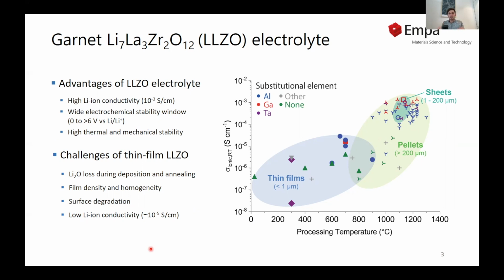On the lab bench, they are typically processed in the form of millimeter-thick ceramic pellets, which are sintered at temperatures of about 1200 degrees Celsius for prolonged times. But if you want to build this material in the form of a thin film, for constructing a thin film battery with LCO, we face several challenges. In this chart, I summarize the typical processing temperatures for thick pellets and sheets and vacuum processed thin films. What we observe is that typically thin films are processed at much lower temperatures, 400 degrees below the standard temperatures for pellet sintering, but at the same time, they also show much lower ionic conductivities,